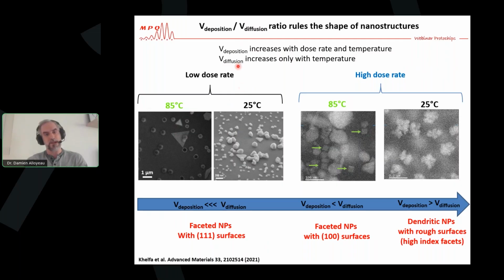At low dose rate, so low growth speed, you give a lot of time to the system to reconstruct. In both cases, low temperature and high temperature, you are dominated by surface diffusion, and you reconstruct nanoparticles that are mostly made of 111 surfaces, which are the most stable surfaces in gold, in FCC systems, most generally. And when you work at high dose, I've already shown you that at 25 degrees, you grow nanoparticles that are dendritic with rough surfaces, with high index facets. So you reconstruct facets that are theoretically not stable because you are dominated by kinetics.